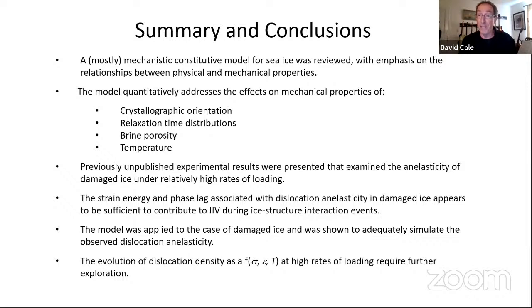And the model, oddly enough, as derived from the lab experiments, pretty much captures what we see at large scale on the floating ice. So the microscopic, the dislocation scale anelasticity doesn't go away simply because you have a large scale. It still operates as a function of the dislocation density that's there and the applied stress and the temperature. I just didn't think I had time to get into it here. But our experiments directly show that the model works and that these dislocation processes operate over many orders of magnitude of scale. I'm real confident in that. Yeah, interesting. Yes, thank you.